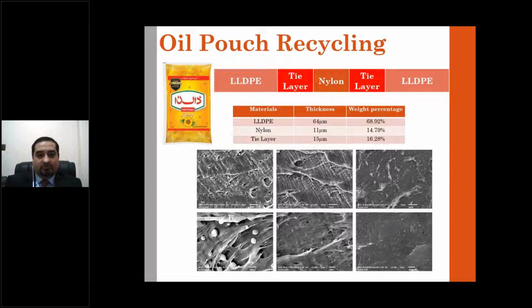Okay, so the recycling of multi-layered structures on its own is not a good option. So what we can do with these multi-layered structures is we then have to separate them out. Separating is another problem on its own. If you try to separate them out, you first of all have to remove the internal vapor deposited aluminum layer. You then have to separate out the adhesive.